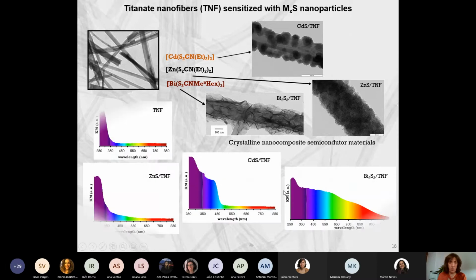Of course, this is interesting, but as I told you before, we are more interested in the photo behavior of these materials. These are the absorption spectra, and here we start to have absorption in all the visible range. In the case of cadmium sulfide, we see the contribution of the CdS crystallites to the absorption of the material, and here we can see the contribution of the naked surface of the titanates. In the case of zinc sulfide, the difference is not so evident, but this material is very interesting when we are looking for a material that contributes to reducing the recombination rate. And that's why we use zinc sulfide.